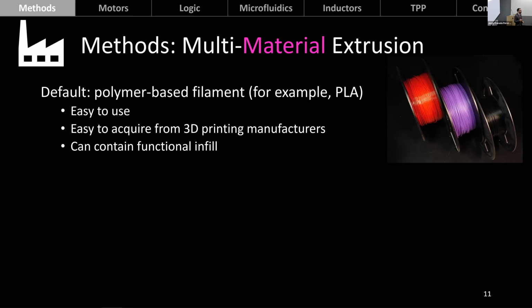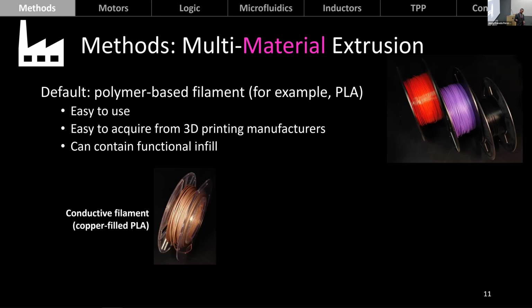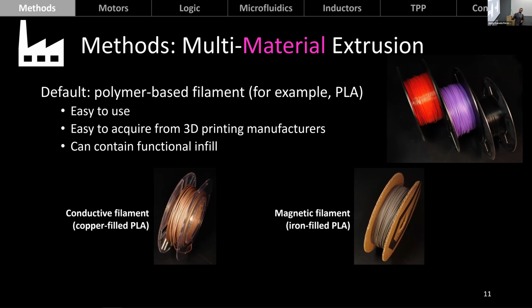Now, this is particularly important because many applications that are out there for multi-material extrusion usually focus on printing with the same plastic but with different colors, which looks pretty nice, but there's a lot more that we can do with it. If we add functional particles of functional materials into these filaments, we can make functional filaments that we can print with. For example, there's this conductive filament commercially available that is PLA doped with copper particles. And there's also a magnetic filament that is, again, PLA doped with iron particles.